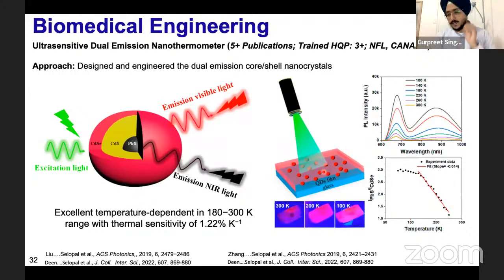wavelengths. And by using this especially designed core shell quantum dot, we obtain excellent temperature dependency in the range of 180 to 300 Kelvin with a thermal sensitivity of 1.22% per Kelvin, which is also a record for this type of technology.